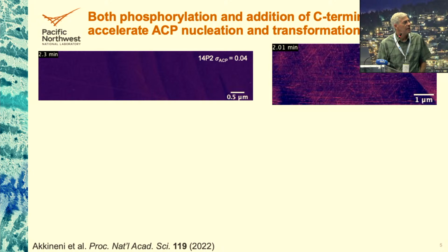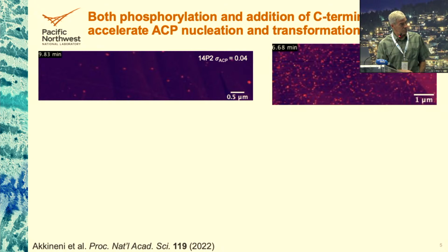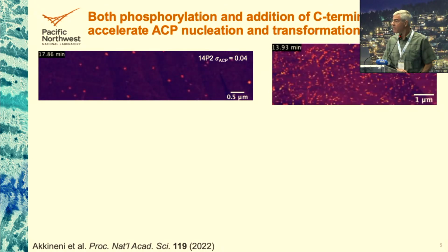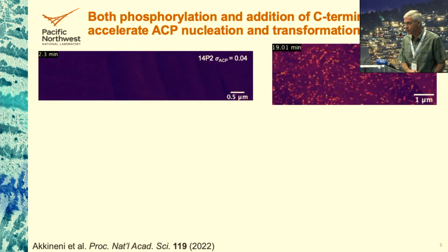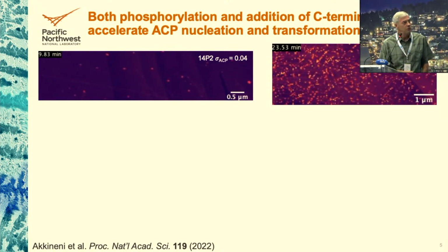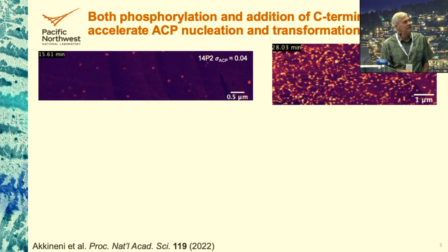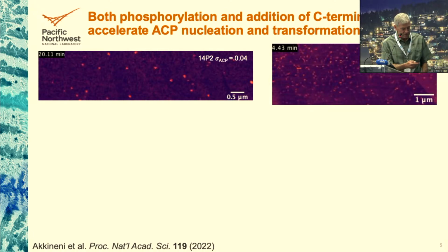So we did nucleation experiments. These surfaces are now fully covered in these ribbons. And I'm showing you two, one that's not phosphorylated and one that is. It's just the 14P2, the amyloid region. And you can see that they both cause nucleation, but at very dramatically different rates. So the phosphorylation has a big impact on nucleation. And eventually you can start to see the outlining of the ribbons as more and more nuclei form.